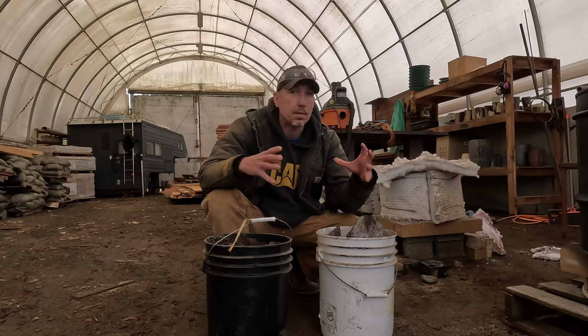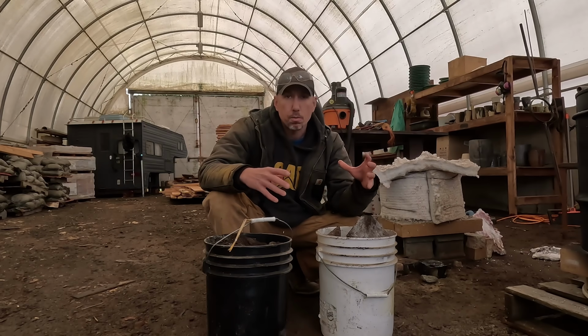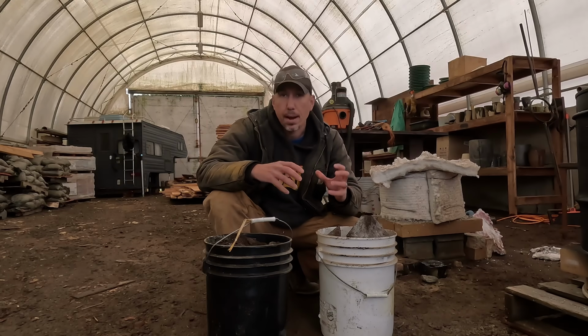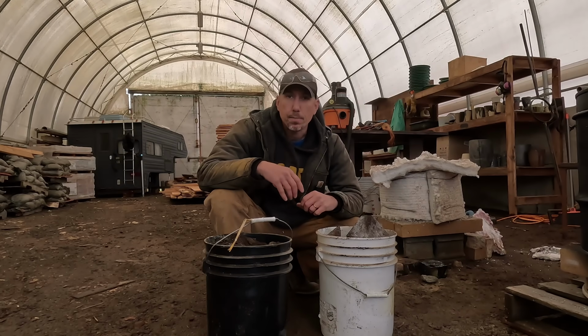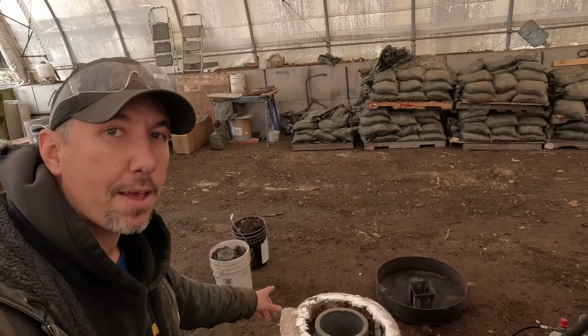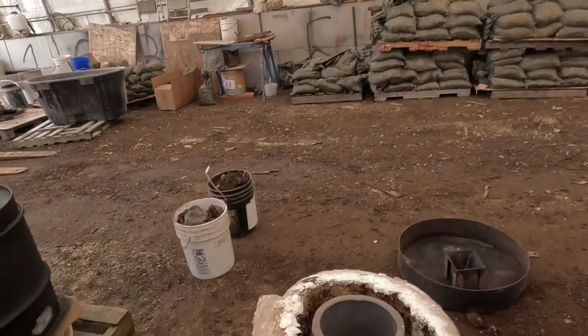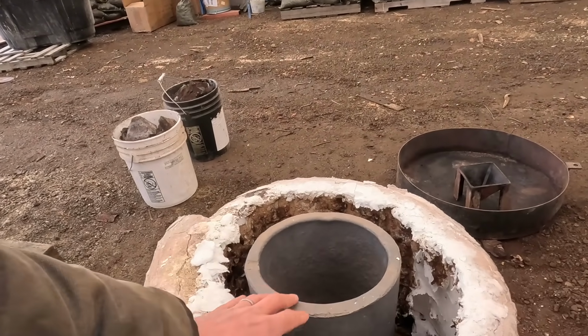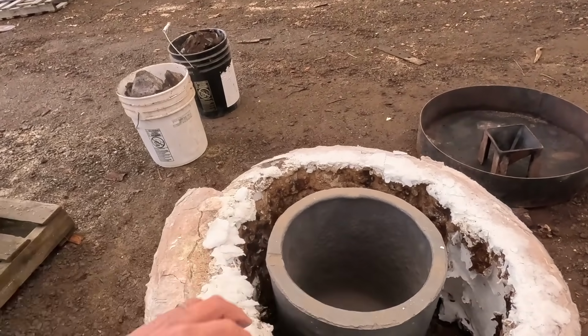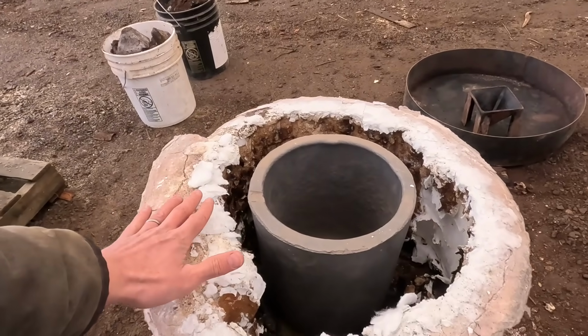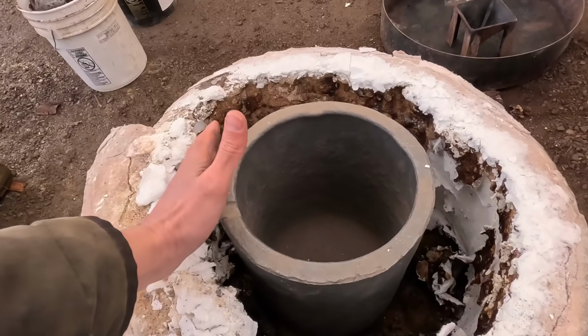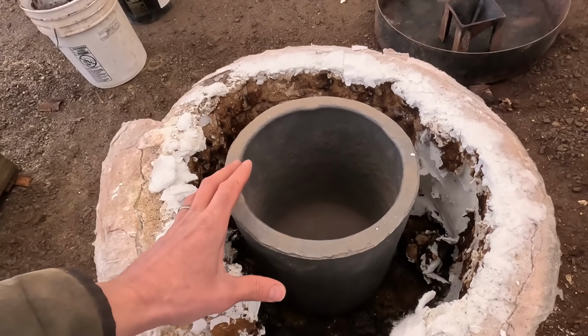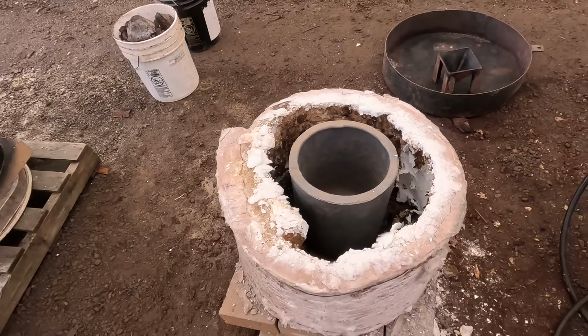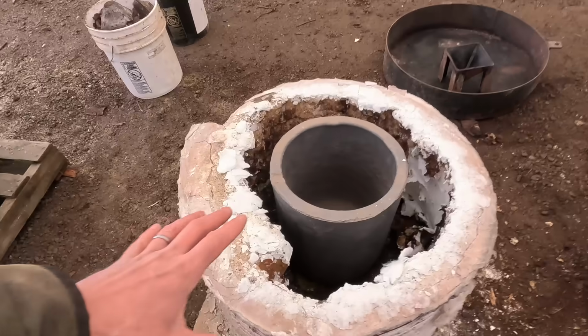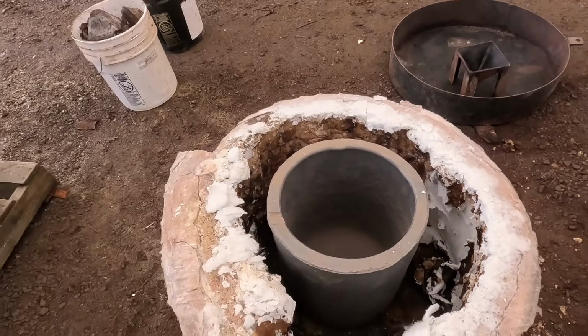So today I'm gonna take some of my larger crucibles and a larger cone mold. We'll smelt all this down, use some chemistry. So let's get some crucibles loaded up with this stuff and see what we can find. We're gonna try this number 30 crucible here. This is probably too big for this little furnace, but hopefully I can get it so it sits down below the rim here. I'm using this crucible just for the volume. I wanna smelt down as much as I can at a single whack here. So let me see if I can get this to fit in this furnace, and then we'll load it up with slag.